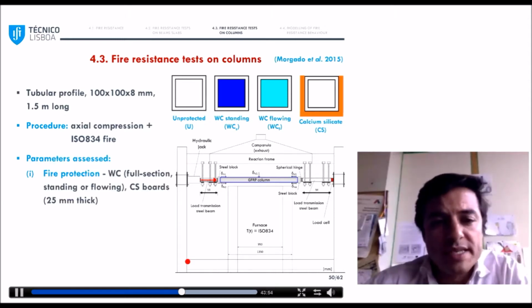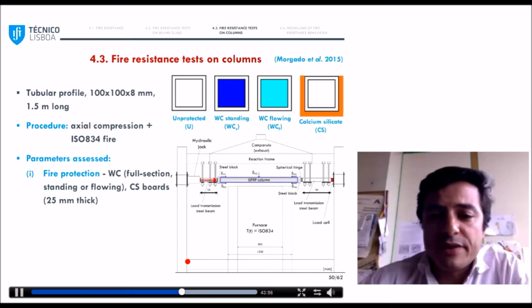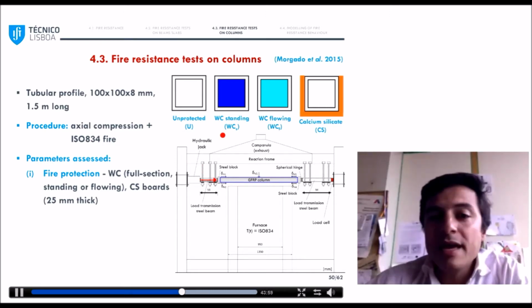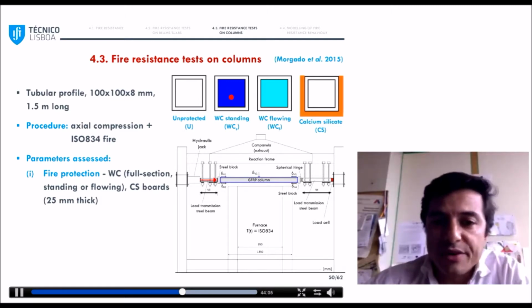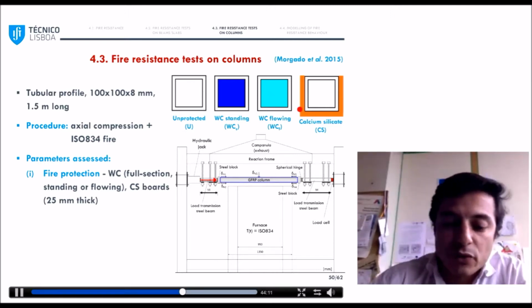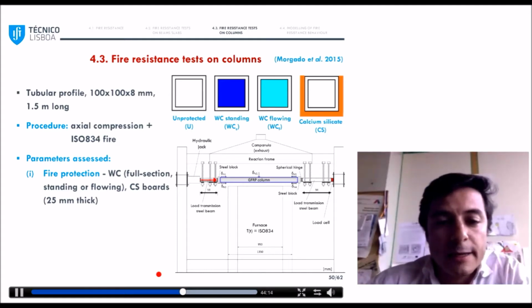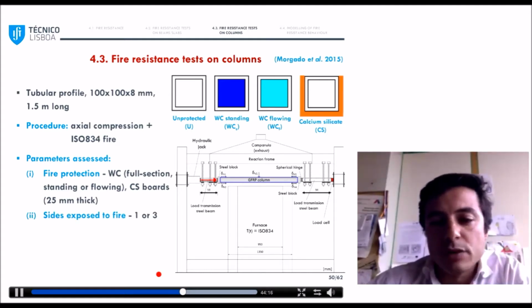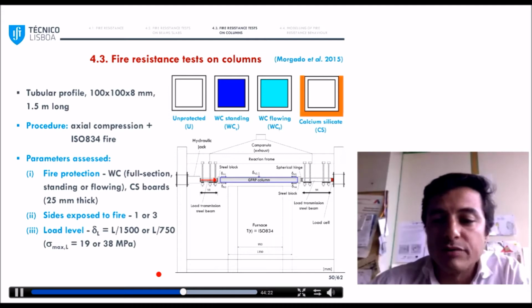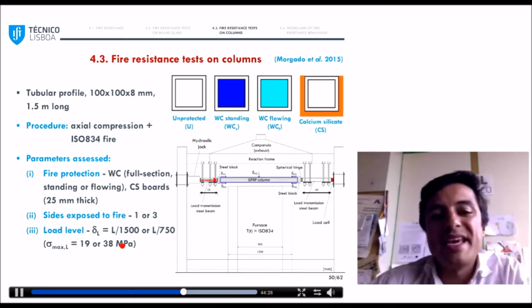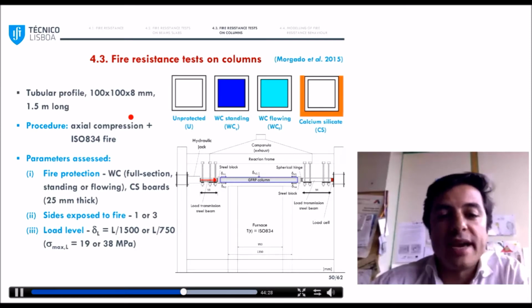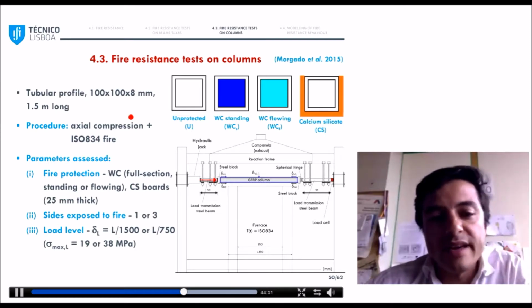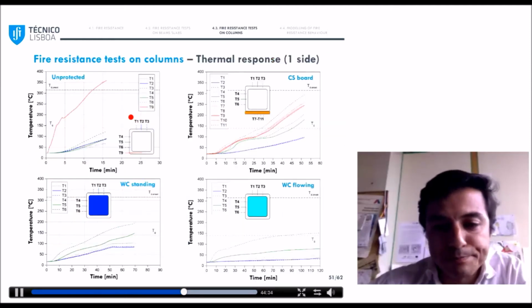As protection, we assessed again different fire protection systems: water cooling, now with the full section, so the entire cavity filled with water, either standing or flowing, and again calcium silicate boards, because they had performed quite well with the beams. As in the previous experiments, we also assessed the number of sides exposed to fire, 1 or 3, and the load level, as a function of the actual shortening as a function of the column height, so height divided by 750 or 1500.